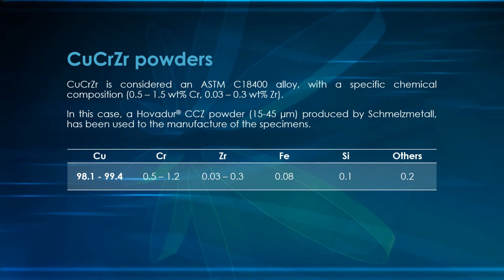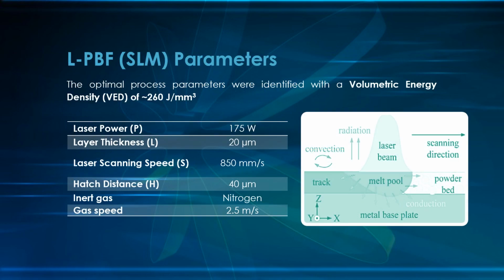Copper chromium zirconium powders have the nominal composition shown in the table. So this alloy, the powders used contain a small amount of chromium and zirconium necessary for age hardening. The powders used have a size varying over the range 15-45 micrometers. In this slide, you can see the parameters used for the printing process. So you can see the values of laser power, layer thickness, hatch distance, and the optimal values of the process parameters were identified as the ones producing a volumetric energy density of about 260 joule per cubic millimeter.